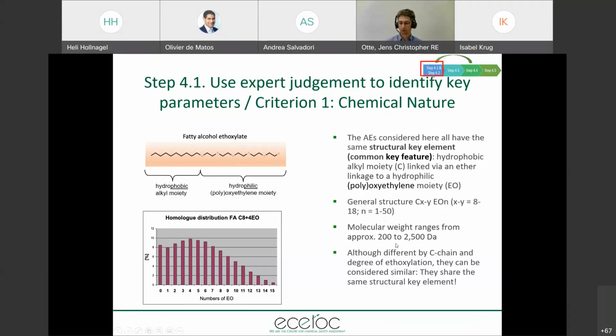The molecular weight is given here from approximately 200 to 2500 Dalton. And although different by C chain and degree of ethoxylation, they can be considered similar because they share the same structural key element, which is given here on the left. And one example on the left downside, you see the homolog distribution of a fatty alcohol that would be called C8 EO4, which means that the C chain length is about 8 and the ethoxylation degree on average is about 4. But if you see this, even if it's 4 on average, there are many, many other species in that mixture. So there is always a mixture, and this mixture is two-dimensional, which means varying in C chain length and ethoxylation degree.